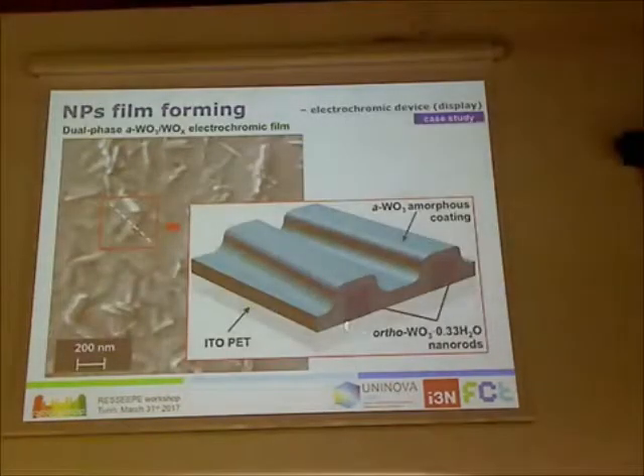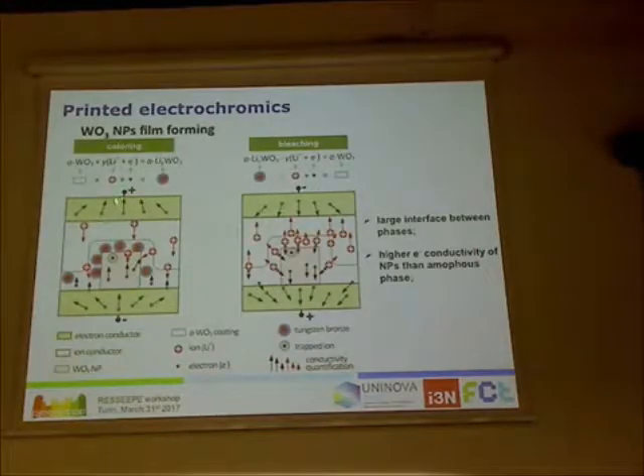Why is this structure important? As I mentioned before, when the reaction starts, the ions come from the counter electrode and enter the tungsten oxide. This reaction promotes the reduction of tungsten oxide and the change in color. But to keep the charge neutrality and assist this reaction, you need to inject electrons from the other side. So the electrons need to travel to the electrochromic layer and reach the site where the ions are coming in.